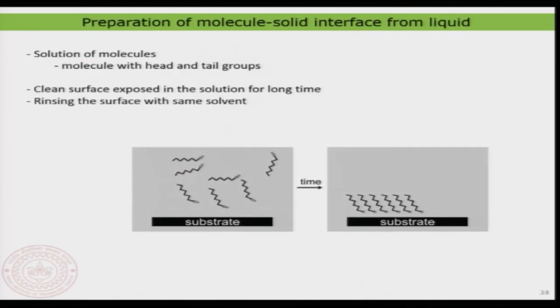In the solution based method, what you do, particularly with molecules with a head group and tail group, is this: I have an example here where you have an alkyl chain connected to an SH group, a thiol group. So you can prepare a solution of this particular molecule, immerse the crystalline substrate where you want to deposit the molecule inside the solution, and allow it to stay there for some time. Then you would find that the sulfur starts to link to the surface and you can form a self-assembly. This is particularly suitable for gold 111 surfaces. But even otherwise, if you have strong functional groups like acid groups, aldehyde groups or amine groups, you can use gold as a substrate and form this kind of layer.